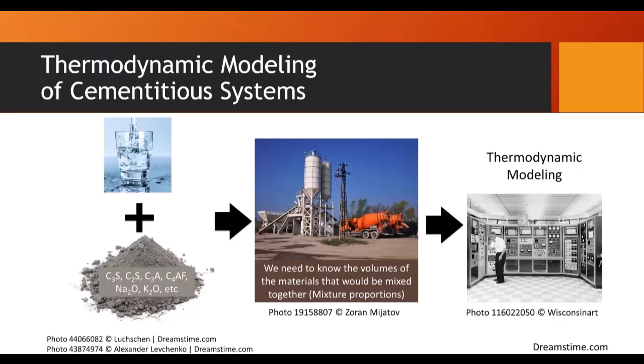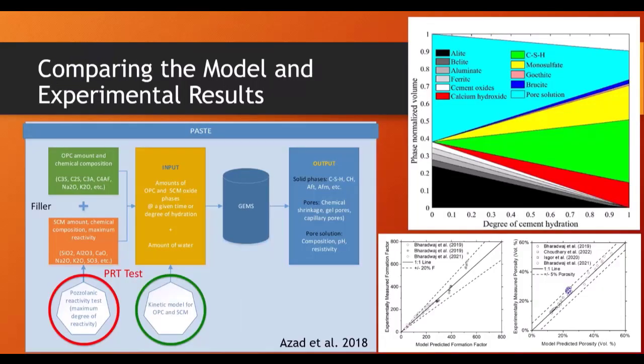We have an approach where we can do this using thermodynamic modeling, where we can take the chemistries of the materials that we're working with, we can actually simulate the performance, all right, and get the overall qualities of our concrete. So we start out with the chemistry of our cement. We can put fillers in, we can put SCMs in, and what we really need to be able to do is to quantify the reactivity of the pozzolans that we're talking about.